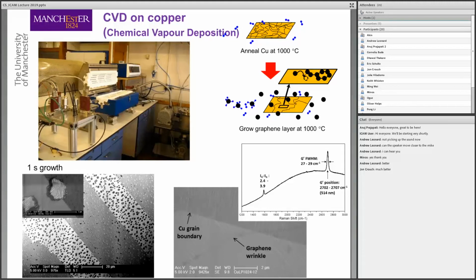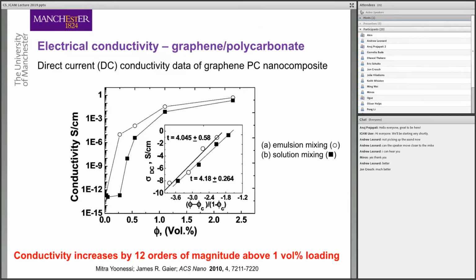And if we look at the electrical conductivity of this graphene reinforced polycarbonate, we can see its conductivity increases by 12 orders of magnitude, where you have only 1% by volume graphene platelets. Again, there you can see that the performance depends very much if you have the emulsion mixing or solution mixing of your graphene. So straight away there, the way you fabricate it, the way you mix it, has an impact on the performance of your composite.